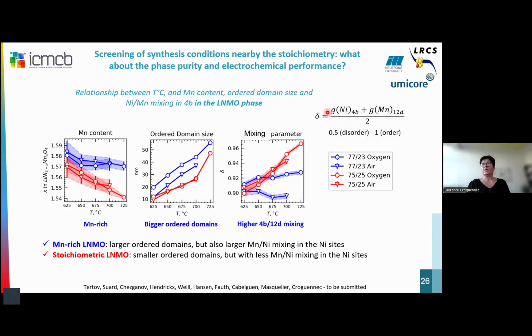This parameter here is a kind of scale for the amount of mixing between the two sites. When there is no mixing, this parameter is 1, and with the increase of the mixing, we move towards 0.5. So you can see that we have more defects for these manganese-rich materials, despite the bigger ordered domain.